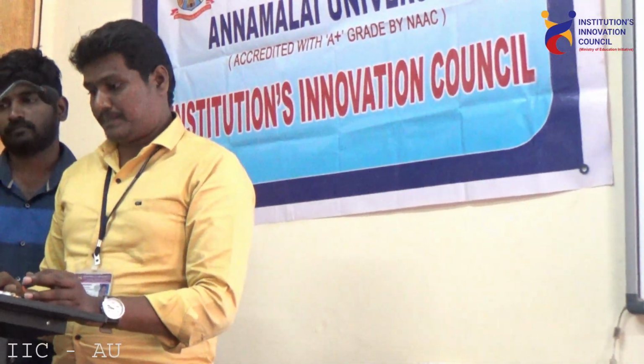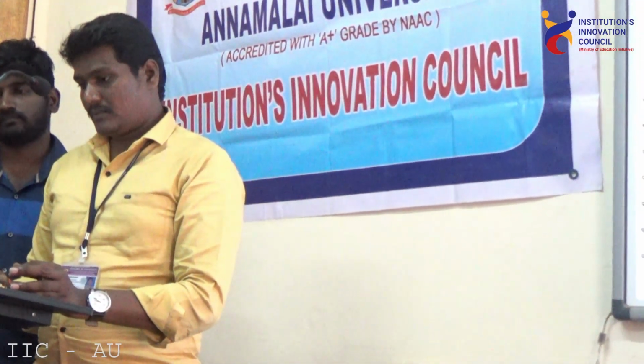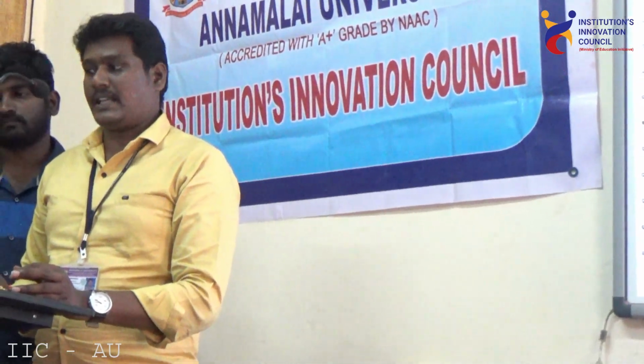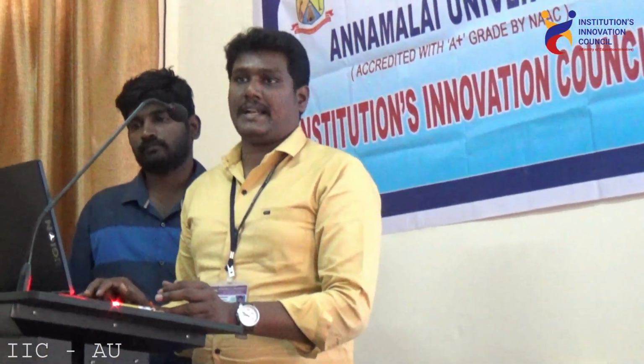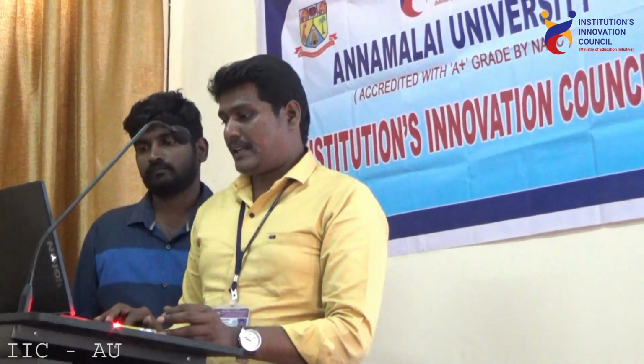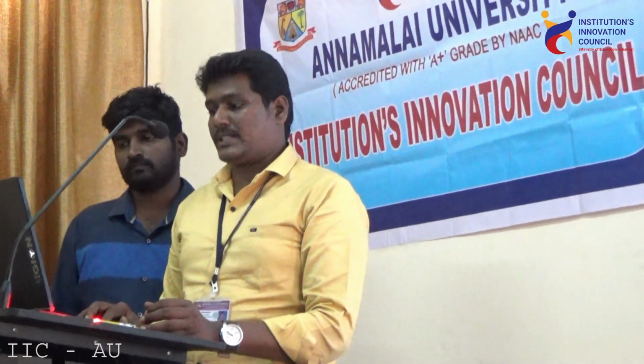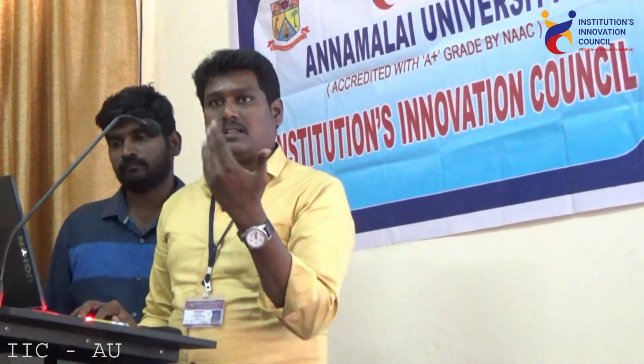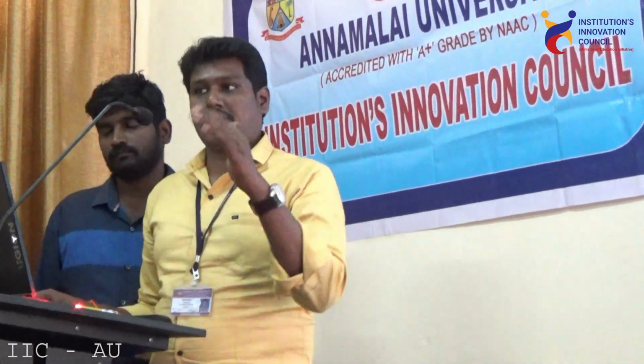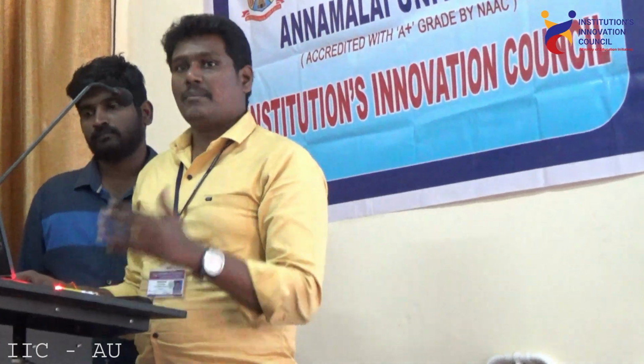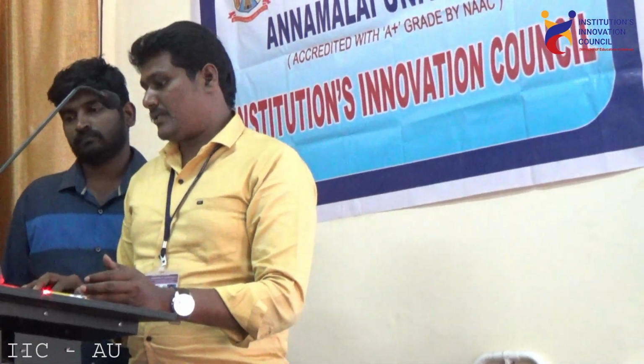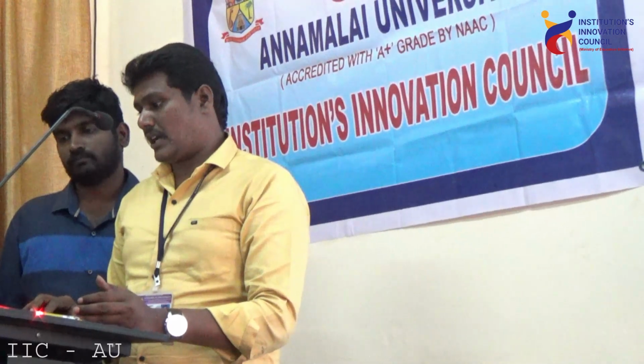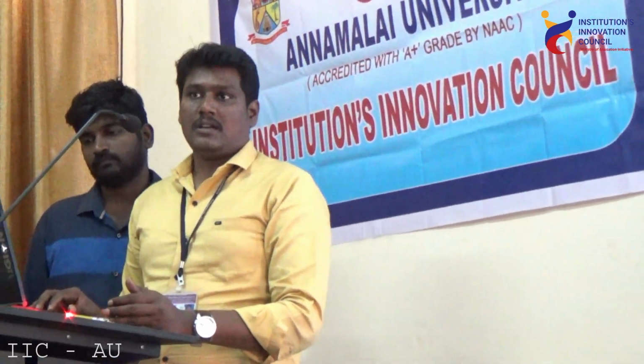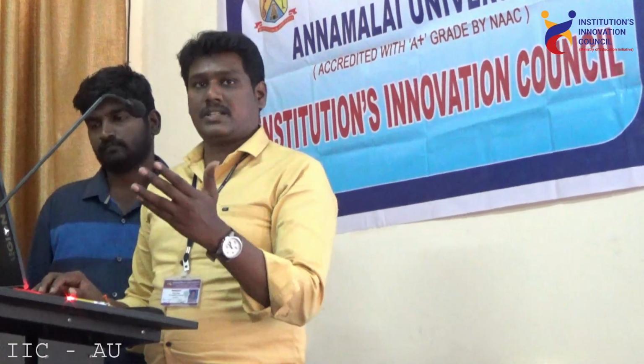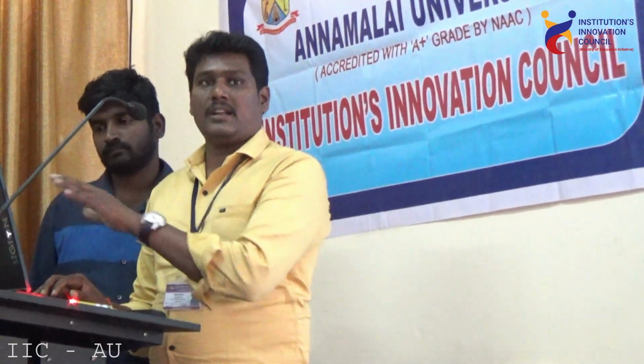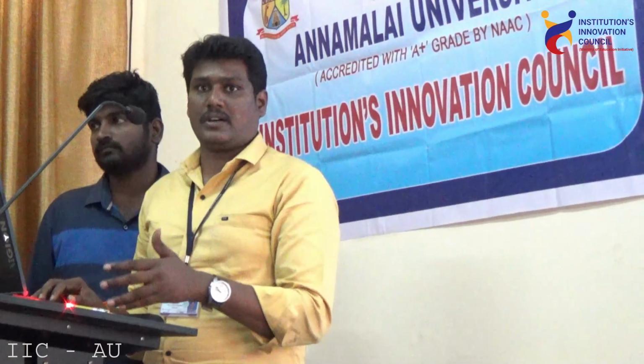In the GMAW process we can see the strength of the component is slightly reduced. We will explain the reason later. And here we could see in the top region the strength of the sample is around 258, which is 8 megapascal higher than the base metal property, and the elongation which we have obtained is around 49.2%, whereas the base metal has a maximum of just 10% elongation.